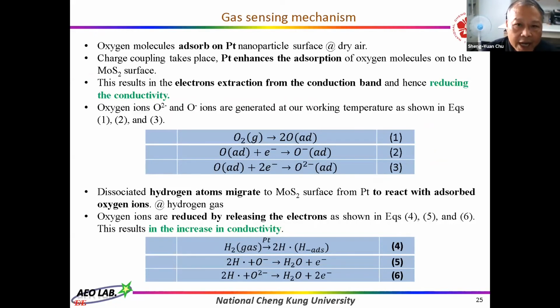Pt will enhance the adsorption of oxygen molecules, and it will cause the reduction of the conductivity by these three equations. And also in step 2, dissociated hydrogen atoms migrate to the MoS2 surface from Pt to react with adsorbed oxygen ions. And also oxygen ions are reduced by releasing the electrons as shown in these three equations. And this will result in an increase in the conductivity.